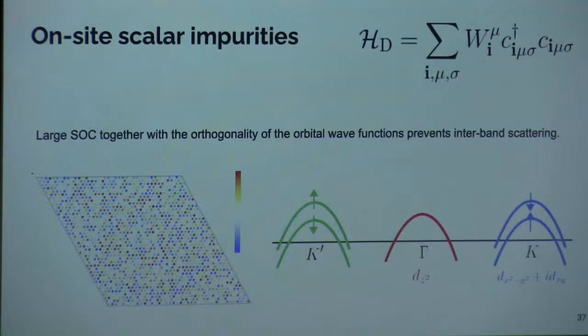And I think that a partial interesting message here is that this even works, and I tested it, if I started with triplet superconductivity, which in a simple model would be completely obliterated by the impurities, but here would remain completely robust. So maybe exploring triplet superconductivity in multi-orbital systems, where you have this type of orbital protection, is a way of getting the triplets to survive the impurities.